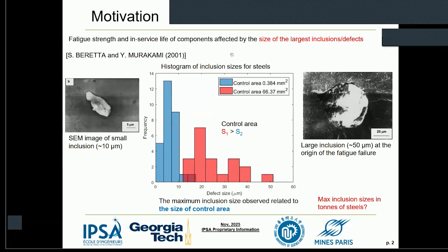Okay, so I begin from the motivations. We know that the inclusion size plays a very important role in the prediction of the fatigue lifetime. It is already a long-term study. For example, we can see some smaller inclusions like 10 micrometers and even larger ones at the surface, like 50 micrometers and so on.